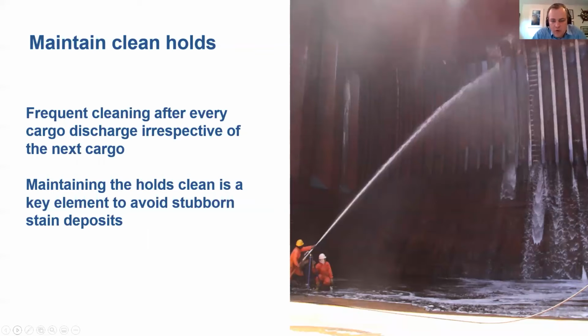So what we recommend, and we always recommend, is to do a frequent cleaning after each discharge of the cargo. That is one of the key priorities, because we hear here and then comments that we don't need to clean because we load a coal cargo on top of a coal cargo that has been there from the previous voyage. But that is not true, because if you clean after each cargo discharge and you keep your holds maintained, then it will also be easier to switch from a dirty to a clean cargo going forward. So it's important to avoid any stains accumulating in the corners or on the surfaces, and to clean them off as much as you can between the cargo sequence.